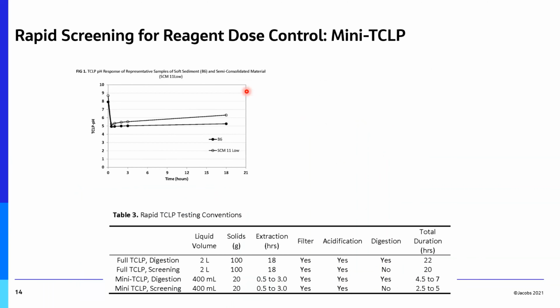So how did we do that? The important thing to recognize here is that sandy, silty materials that are natural in origin, or glass-like, or high in solution aluminum silicates, and not clay, have very little buffer capacity. I actually picked up on this idea from Paul Lear, who works for a stabilization solidification company, because he was looking at lead leaching out of crystal, and he ran an acid extraction test very quickly and found that because glass has no buffer capacity, your pH after about 1 hour is actually the same as your pH at 18 hours. So all we had to do was rapidly acidify this material and then track the arsenic with time.